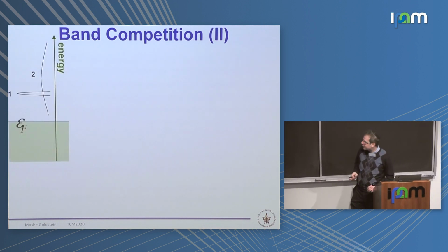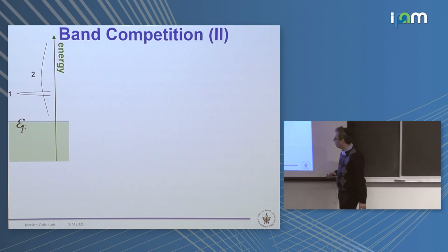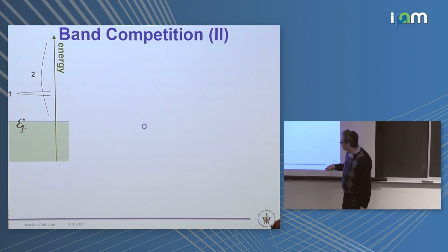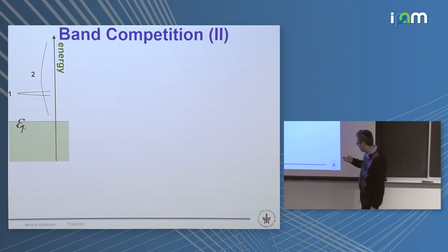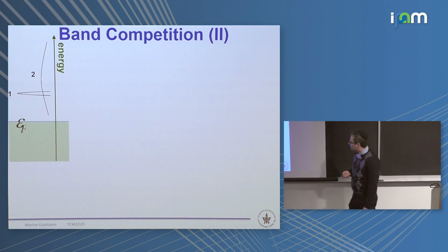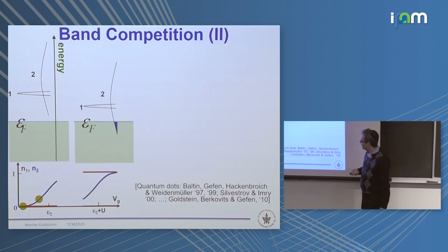What would happen if the bands overlap? So the low mass band has such a low mass that actually it has a density of states which overlaps with that of the band with high mass. Then it could be more interesting. So to see that, suppose I start increasing gate voltage. I start putting in actually particles into band 2, because it has this tail in the density of states. As I do so, I increase the energy of band 1, so it increases in energy. And okay, so I get something like that. This is filled, this remains empty.